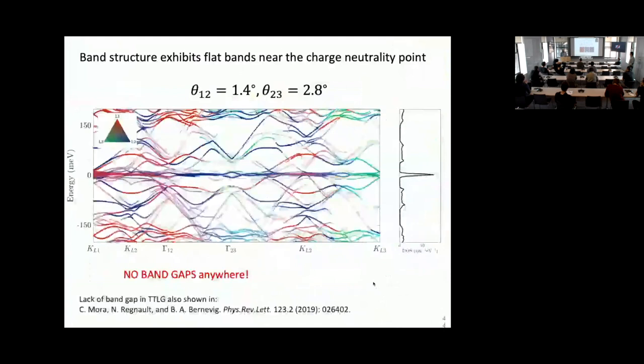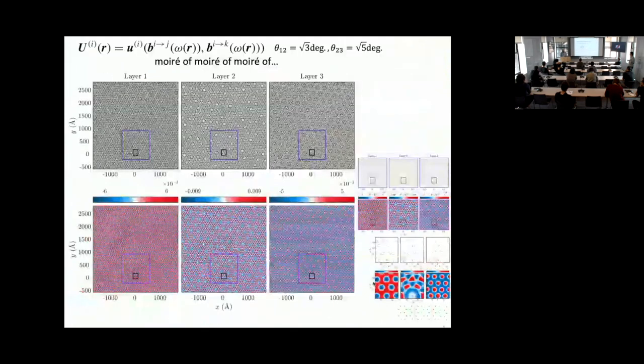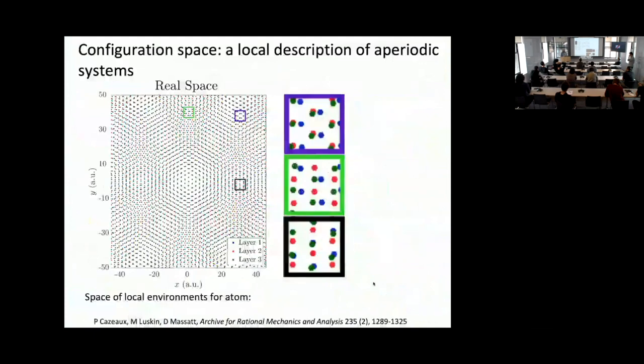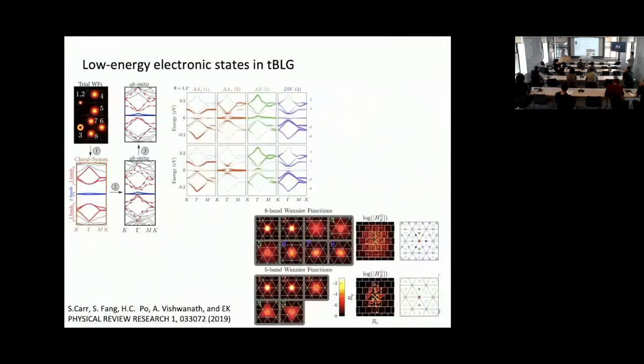The reason is the following. If you look at the density of states associated with these bands, the number of electrons associated with these bands is minuscule, really tiny. The overall Moiré unit cell is huge, of the order of tens of thousands of atoms. And the number of electrons associated with these bands is just a few electrons in tens of thousands of electronic states. So I think changing the occupation of these bands is not going to affect the overall structure. Does that make sense? Oh, that makes perfect sense.